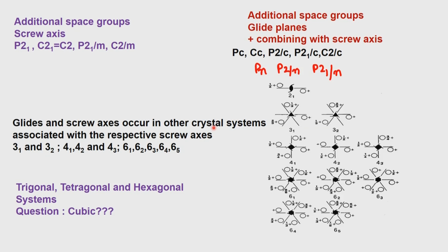This will have a very important repercussion when we see the X-ray diffraction patterns, because we analyze the X-ray diffraction patterns with respect to the various values we see from the presence of these reflections, and the presence or absence of these reflections is governed by the way in which this space group develops. And therefore, some of these elements, the presence of the C centering and the I centering, will introduce what are known as systematic absences. So also the presence of the 2-1 screw axis and the mirror and the glide planes.